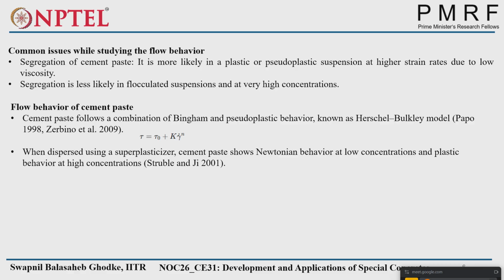Right, correct answer. So we'll have a certain amount of trapped water inside the cementitious particles. When we add the superplasticizer, that will create repulsion between the cementitious particles. That repulsion will release the trapped water. That trapped water is responsible for giving the flow of the material and reducing the yield stress and plastic viscosity. And that's why it shows the Newtonian behavior.